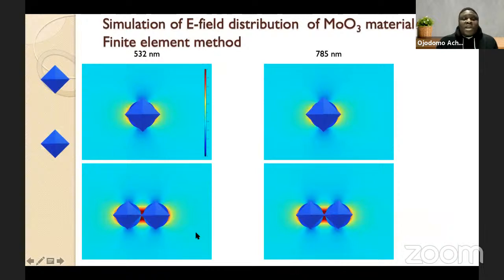So in order to fully understand what happens with the plasmonic properties of this material, we have done some simulation using the finite element method. We're able to see that, yes, the catalyzed SERS effect that we experience is because we're able to bring together, via the sandwich immunocomplex formation, two or more SERS nanotags to form a very good localized SERS hotspot region. As customary with SERS nanotags, we're able to simulate the intensity of the plasmonic resonance, or the electromagnetic field distribution, that is generated at different laser excitation.